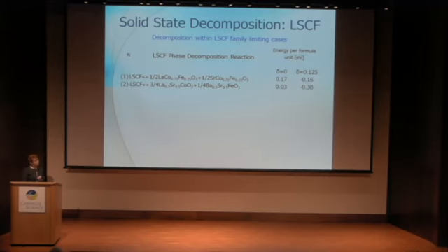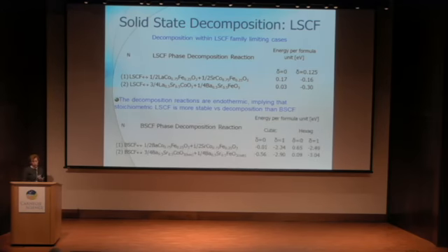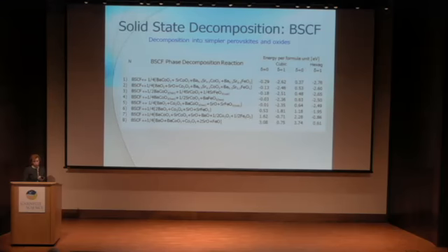Then we went further and wrote even more equations for LSCF. And we saw different energies and different dynamics of these reactions. So the decomposition reactions are endothermic, unlike BSCF, which implies that stoichiometric LSCF is more stable versus decomposition than BSCF. And just to remind you of the previous slide, here are the energies. And you can see that for LSCF, even with delta equals 0, energy is endothermic, while for BSCF, it's exothermic for cubic phase, and it will decompose.